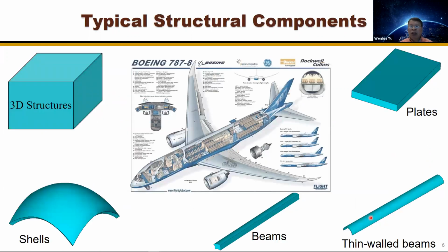So to avoid the issues associated with bottom-up multiscale modeling, I have been searching for a top-down modeling approach from the system perspective. Fundamentally speaking, for a structure, no matter how complicated it is, the structure analysis basically comes down to a combination of 3D solids, if all 3 dimensions of that component are of similar size, or plates and shells, if some component has 1 dimension much smaller than the 2 other dimensions, and also beams, if we have 1 dimension much larger than the 2 other dimensions, or thin-walled beams, if all 3 dimensions are of different orders of magnitude. And this is basically our mathematical idealization.